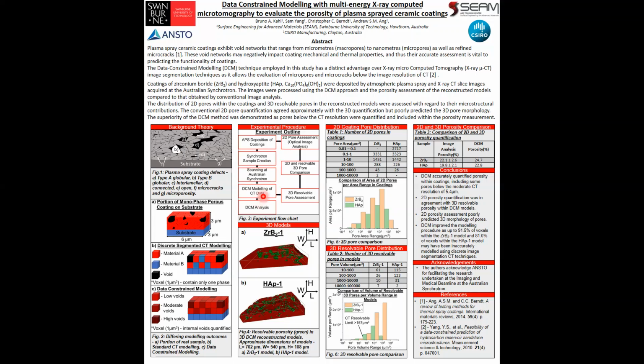Data-constrained modelling was then used to obtain 3D reconstructed models, as shown in Figure 4, and the resolvable porosity of the models displayed in green was inspected. A comparison of the 2D pore assessment of the coatings and 3D resolvable pore assessment of the models was then executed and revealed a large disparity.